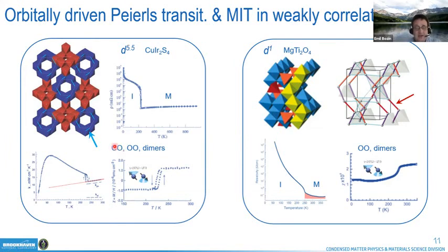There is actually charge ordering, orbital ordering, and spin dimerization taking place in this system. And then its sort of electron counterpart is the titanium version of the system, which has one electron per transition metal and which in the ground state forms these helical structures, again composed of titanium dimers in this case. And as it happens in these systems, the high temperature metallic regime is actually highly anomalous, as can be seen by a number of properties. So for example, here I show thermal conductivity, which is glass-like at high temperature, as well as relatively poor conductivity in this titanium system.